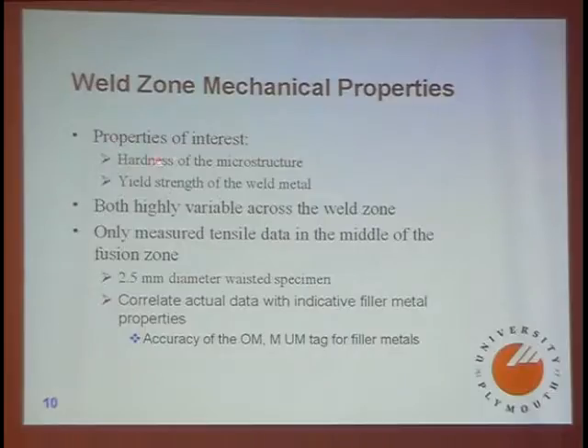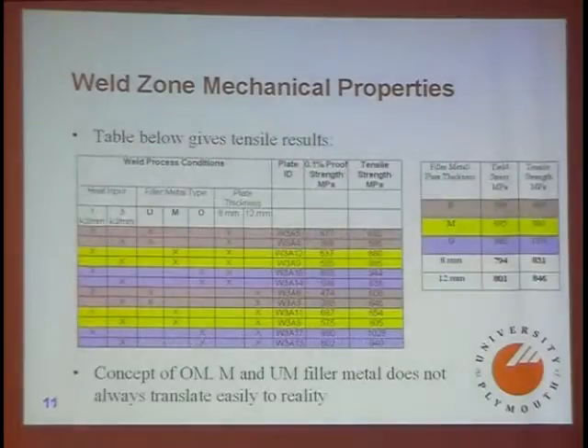So properties of interest are the hardness of the microstructure, yield strength of weld metal. They're both highly variable across the weld zone, and it's only possible with the equipment we've got to measure tensile data in the middle of the fusion zone, and you can do that with a 2.5 millimeter diameter waisted specimen. And then you can have a go at correlating the actual data with indicative filler metal properties. Just have a look at the accuracy of that tag of overmatched, matched, and undermatched filler metal. It turns out that that is not necessarily super close.